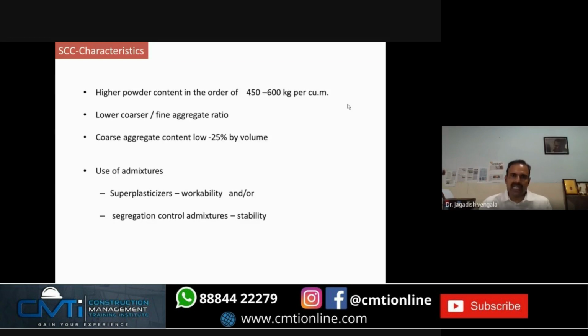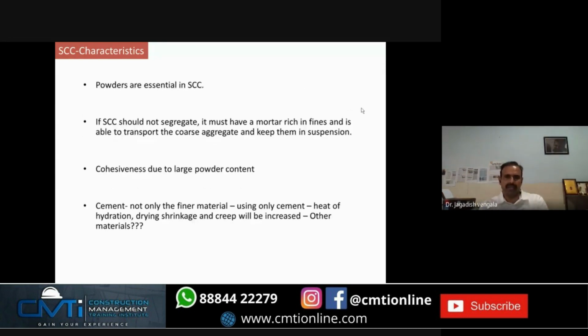So in case of SCC, it is equal. Out of 1900, 850 is fine aggregate and 850 is coarse aggregate, something like that. So either equal, or sometimes 700 is our coarse aggregate and 750 is our fine aggregate. So that is how the mix is self-compacting. And the coarse aggregate content is about 25% of the total volume. You have to use both stability and workability admixtures. As I mentioned, powders are crucial. You need more powder content, more paste content in self-compacting concrete when compared to normal concrete.